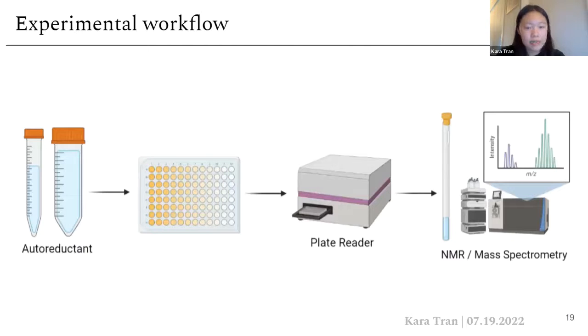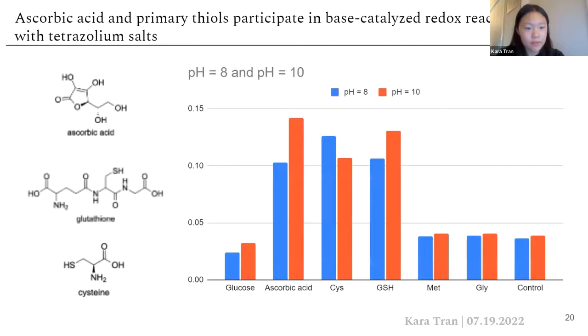We then ran MTT assays of these 7 reductants at different pHs and observed results through a plate reader. And then we identified the mechanism of certain thiol-mediated redox reactions of MTT through LCMS. So here are our preliminary results, which we ran at a pH of 8 and a pH of 10. Observably, ascorbic acid, cysteine, and glutathione show higher reduction at both a pH of 8 and a pH of 10 compared to the others assayed.